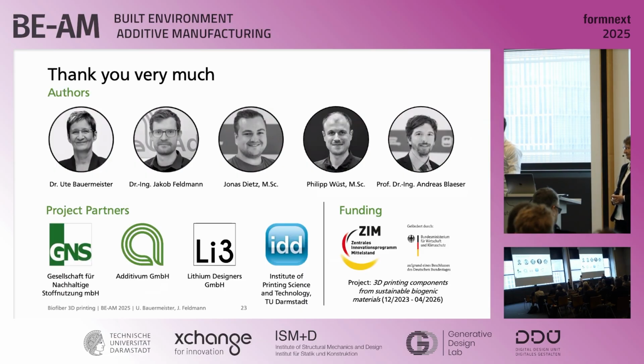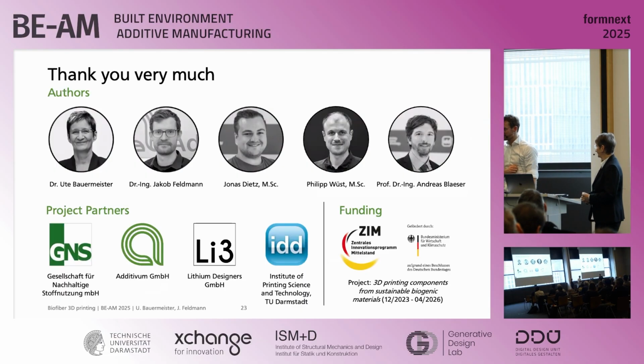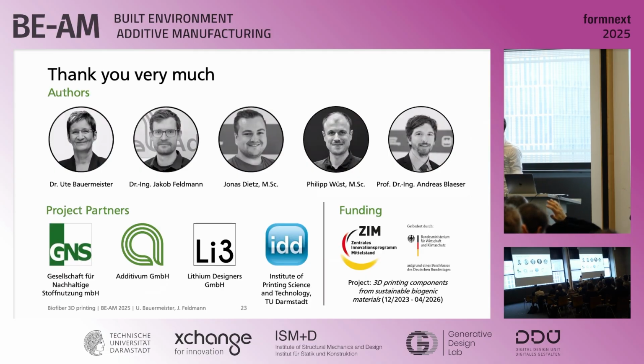Okay, then a question from my side for the urn. Is it fired or is it unfired? It is fired, but not at the highest temperature for that material. So this is bisque fired. So it will dissolve in water, but after a couple of weeks, months. Especially in Germany, you have to fulfill requirements that everything that goes into a grave either comes out of it again in one piece or disintegrates, and after 2 years it has to dissolve, and they do that. We have to guarantee that. So yeah, they're fired, but just at 850 to 900 degrees. But you had quartz transition already at 570-ish? Not entirely, no. That's the thing. They are deep dried, let's say, but they will disintegrate, and there's no transition yet. Okay. But stable enough for the whole handling beforehand, because that would have been a mess. Yeah.